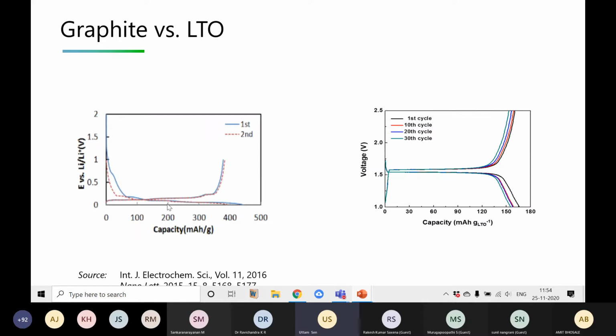Again, if you just look at their standard charge discharge plateau, you can see in case of graphite, it is close to zero. Close to zero means close to lithium, okay, against lithium. That means it behaves very close to lithium. So if we charge or discharge at a higher rate, then it could attain the same kind of performance as lithium. Okay. And in case of LTO, you can see it is quite flat, and the charge discharge plateau is around 1.6 volt against lithium.